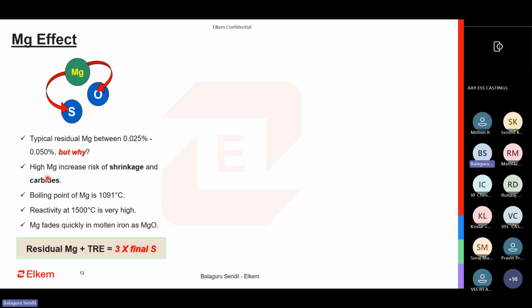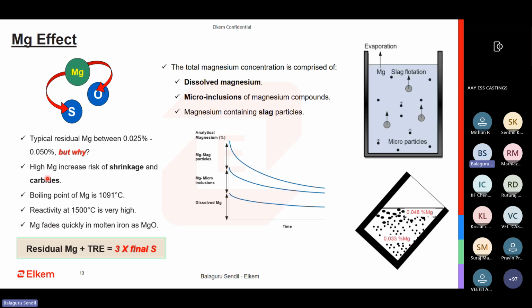And if you are using high magnesium, you're going to burn a lot of magnesium and waste a lot of magnesium, because making magnesium is quite energy intensive. If a foundry does a proper CO2 calculation, if you use more FSM or a high magnesium process, your CO2 will go for a toss. The carbon footprint you generate is going to be drastically affected. Again, circling back, when we say that I need 0.025 or 0.050, what does this particular value mean?